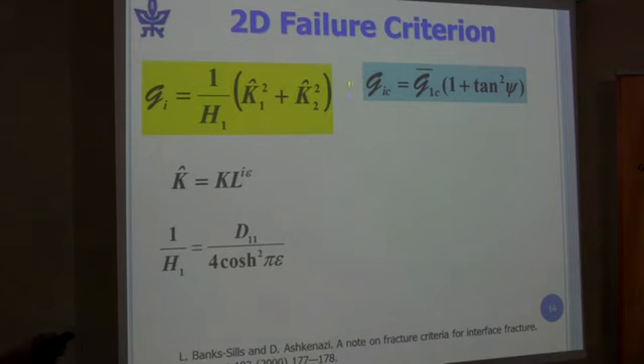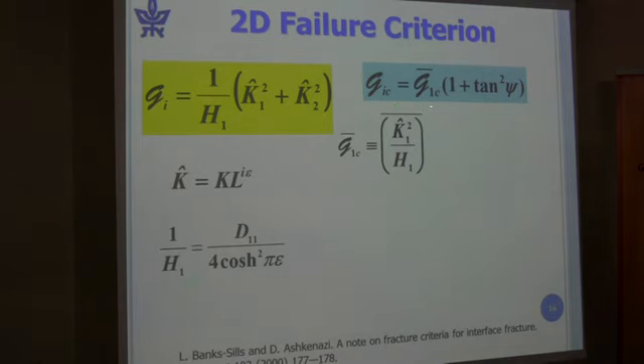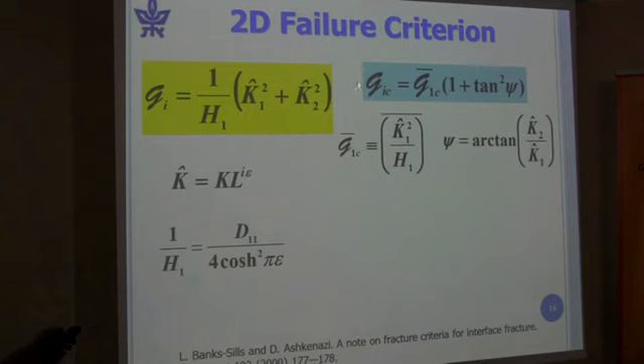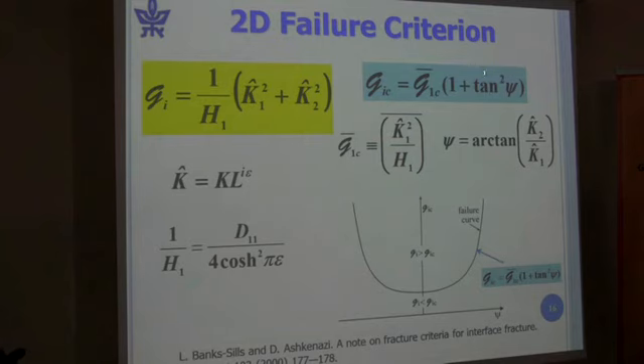So this is the failure criterion. You manipulate this, and I'll remind you what psi is, and what G1C is. We carry out, let's say, 25 different experiments, and we analyze them, and we obtain a value for K1 hat. We square it, we divide by H1, and then we take the average for all of them. So this is an average G1C value, and psi is just the mode mixity, the arctan of K2 hat to K1 hat. So this is our failure criterion, and here is a graph of the failure criterion.